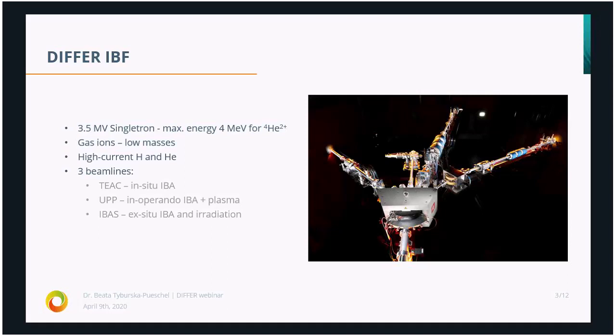And we have 3 beam lines. One of them is TEAC, which is an in situ ion beam analysis chamber connected to the Magnum chamber. So you can expose your samples, for example, to plasma, and then without breaking vacuum transfer them to the TEAC chamber and perform the in situ IBA. This is that line here on your left side.